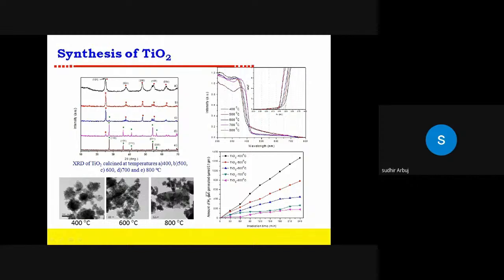We also evaluated its photocatalytic activity to generate hydrogen. Here we observe that the material prepared at 400 degrees centigrade shows the highest hydrogen generation, almost 1200 micromoles per 0.1 gram per 4 hours. As the particle size is much narrower, nanosize, that's why it gives higher hydrogen generation. The TiO2 prepared at 800 gives almost 200, meaning TiO2 prepared at 400 degrees centigrade shows 6 times enhanced hydrogen generation as compared to TiO2 prepared at 800 degrees centigrade. From this study we can fix that we have to prepare TiO2 at 400 only so that it can give maximum hydrogen.